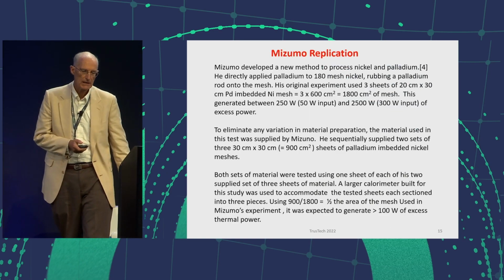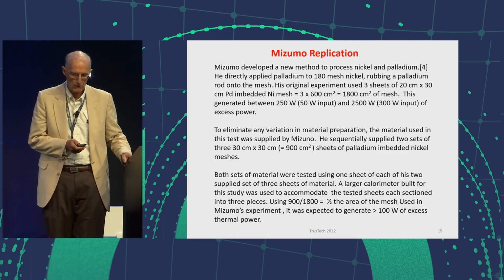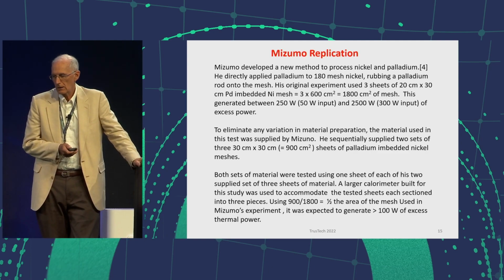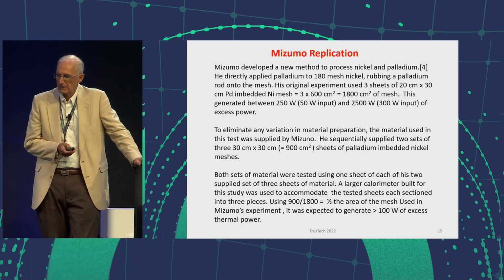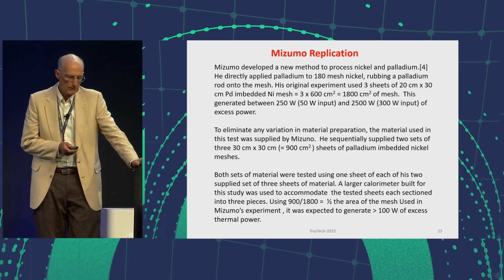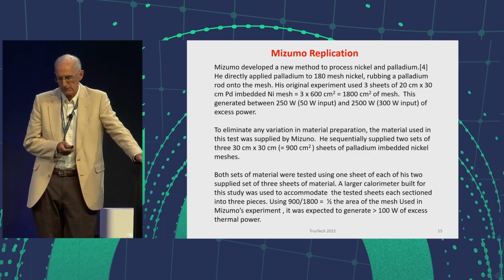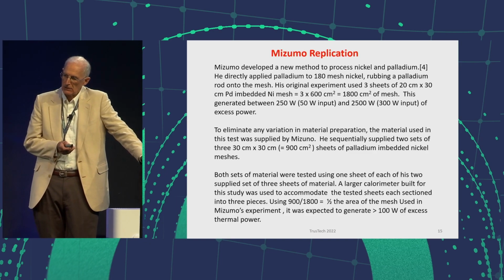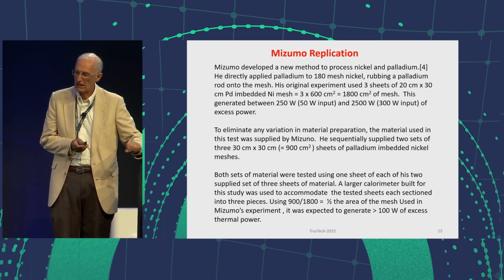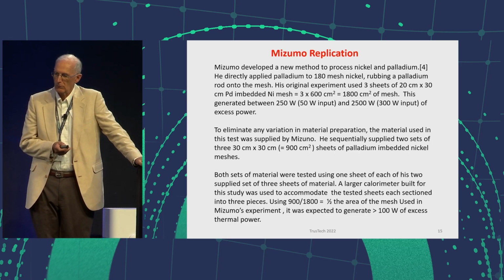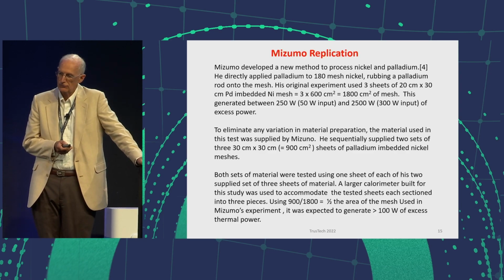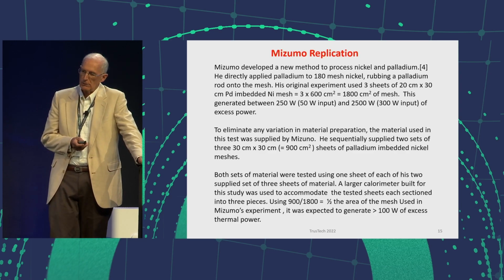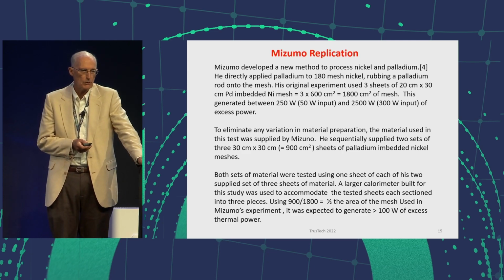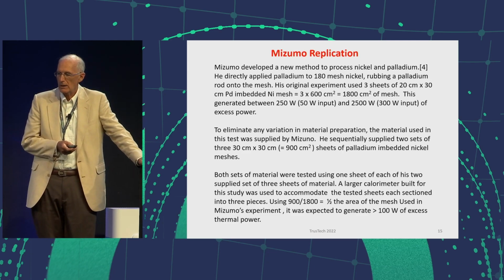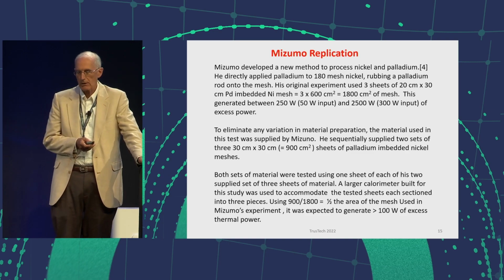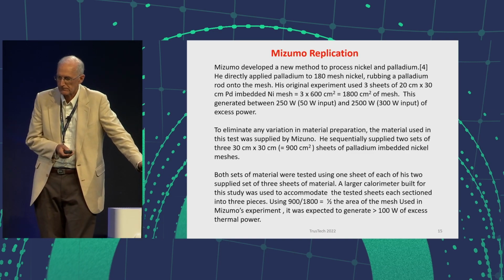Recently, there's been a lot of excitement with results from Mizuno, which were recently documented. Mizuno had a new technique of putting palladium in a nickel mesh by rubbing it onto the mesh. And he was able to, with 1,800 square centimeters of this treated mesh, be able to see 250 watts of excess power with a 50-watt input. And with the 300-watt input, he saw 2.5 kilowatts of power. So it was very exciting results.